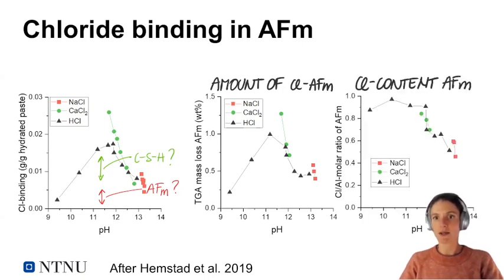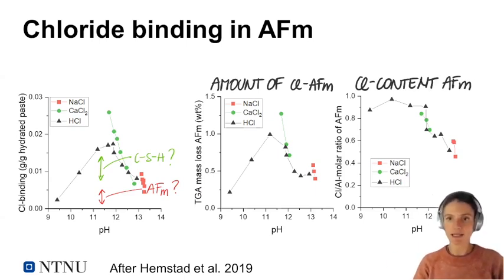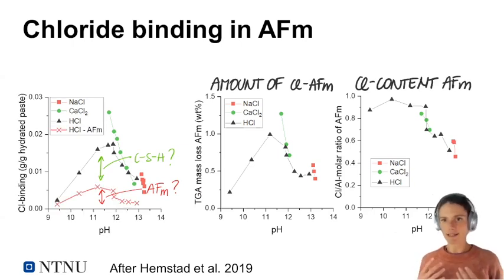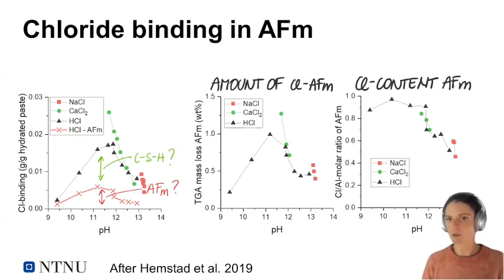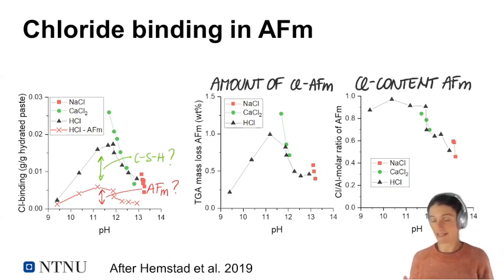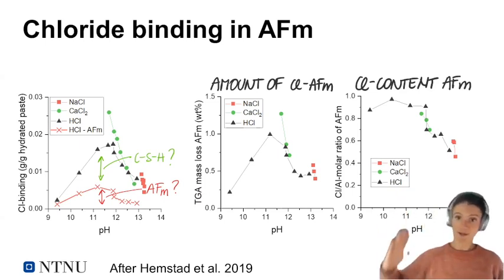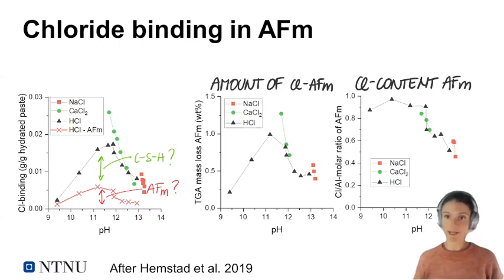He also saw that the chloride content in the AFm changes with pH, and he documented that using SEM-EDS. When we combine these two, we can look at the impact of AFm. So we calculated the impact of AFm on this pH-dependent chloride binding of our Portland cement. What we can see is that the AFm follows this first increase with chloride binding when pH decreases to a certain level, and then it decreases again if the pH decreases even further.